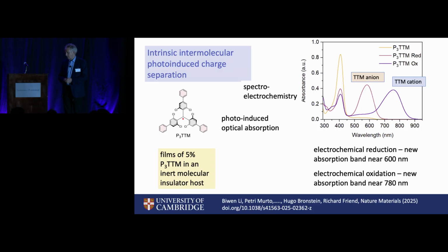The material by itself has strong absorption to about 400 nanometers. If I reduce it electrochemically, the anion absorption peaks at around 600 nanometers. If I oxidize it to form the cation, there's a new absorption. It changes color, and the absorption is now at about 780 nanometers. So I know if I've got electrons or holes on that molecule because I see the color change.